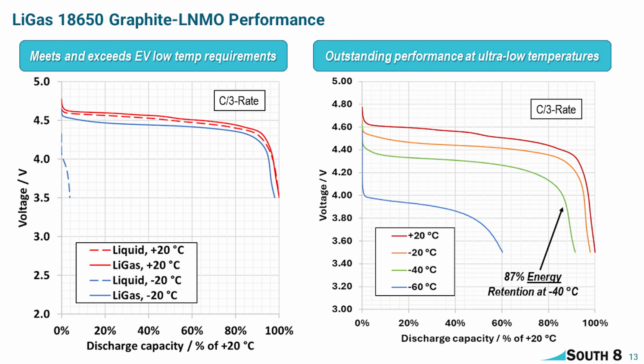When you start to drop the temperature down to minus 20 degrees Celsius, you see the liquid voltage curve just drop right out. That electrolyte is just essentially freezing, or salt is precipitating, who knows what's happening in there. But it's not performing very well. As we all know, the liquid electrolytes just don't do well at low temperature. The LiGas electrolyte shows very little, if any, degradation whatsoever. Really getting essentially all of your energy out of that cell still.